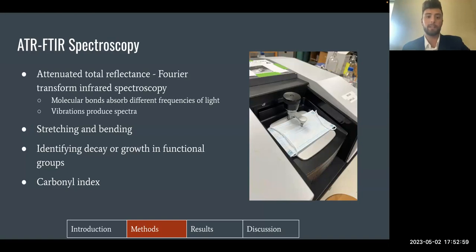The literature states that the carbonyl index, or a carbon double bonded to oxygen, is a useful measurement for polymers such as polyethylene and polypropylene. And since surgical face masks are primarily made of polypropylene, the carbonyl index was chosen to measure degradation in the polymer's molecular functional groups.